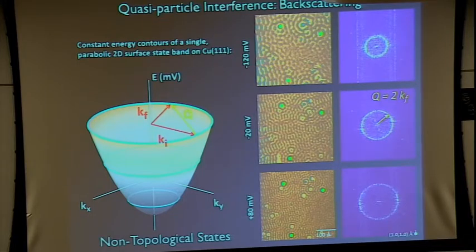That's why the question was about the energy resolution. You modulate the voltage and you measure a modulated current. The finer your voltage modulation, the finer the energy resolution you have of any density of states variation. But if you try to inject an electron at some energy which corresponds to some momentum, and those states are already filled, we can't. So you reverse the bias and you pull those electrons. Oh, I see, so that's why it's positive and negative. Exactly, right. Good. Now you even understand STM.